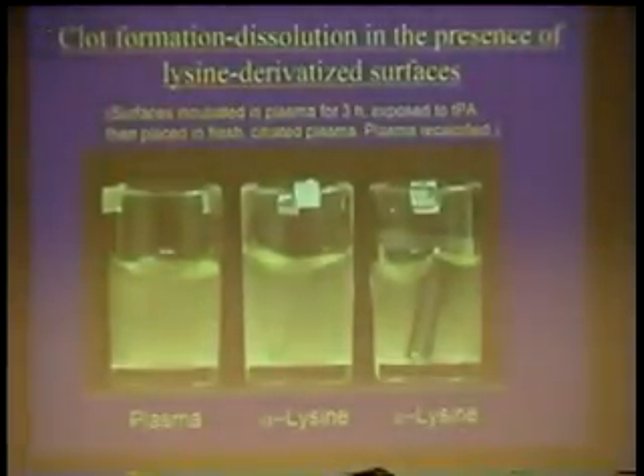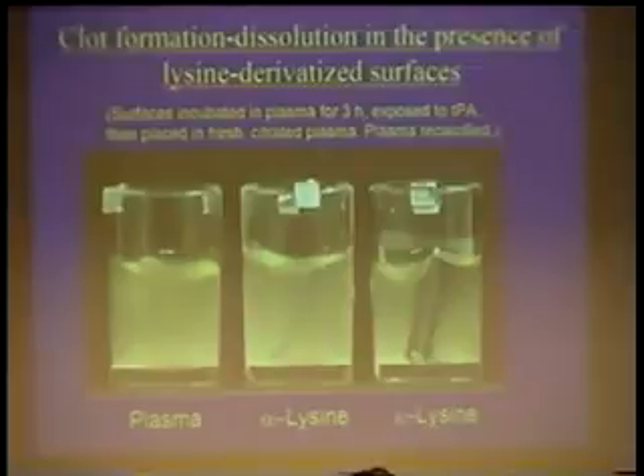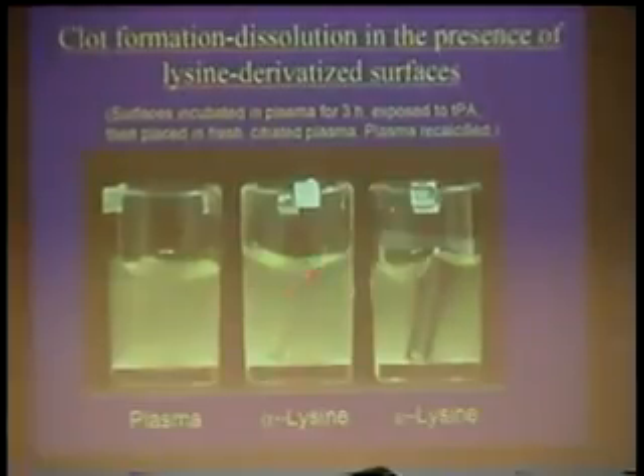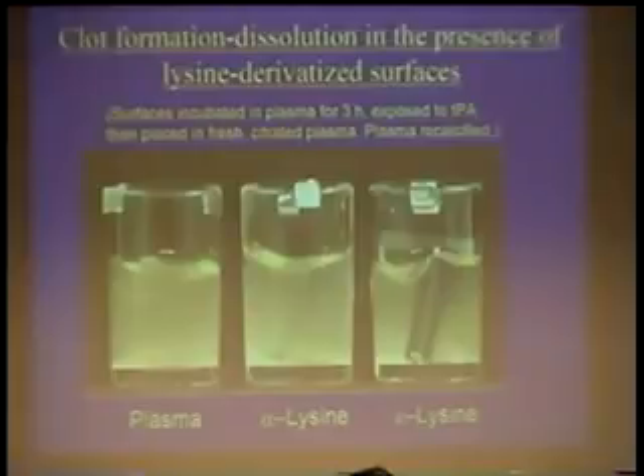This is what that experiment looks like. If you do it, this might be 6 or 7 or 8 minutes into the experiment, something like that. This is just the plasma with no surface, and you see the clot has formed. It's gone all cloudy. This is the alpha lysine surface, so there's no effect. It's basically the same as that. The epsilon lysine surface at that point, the clot here has formed and then it's beginning to redissolve.